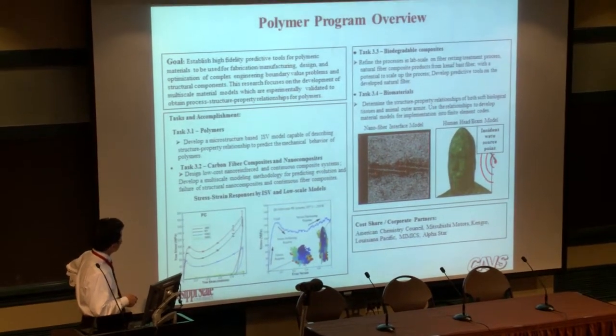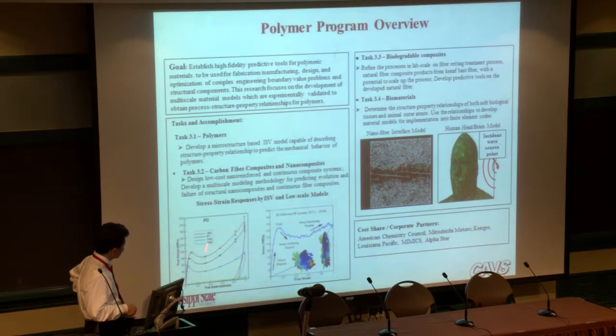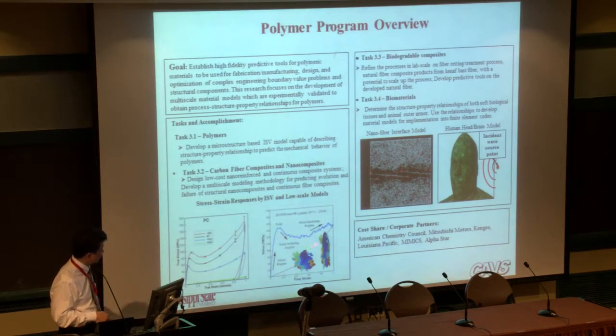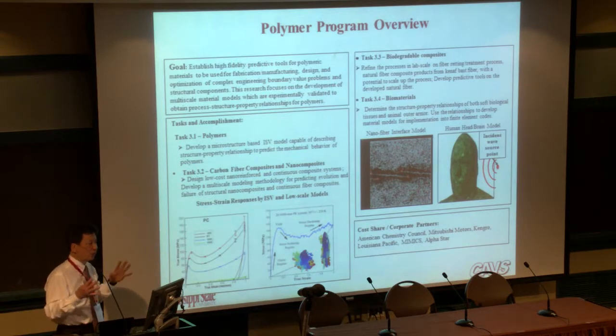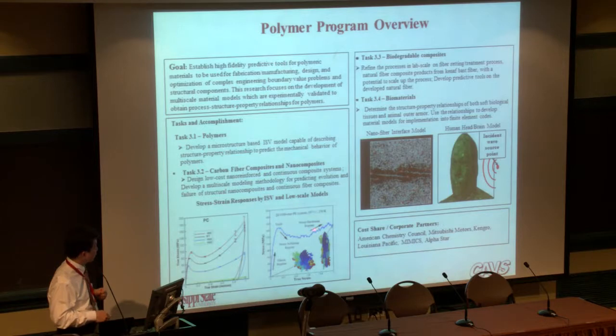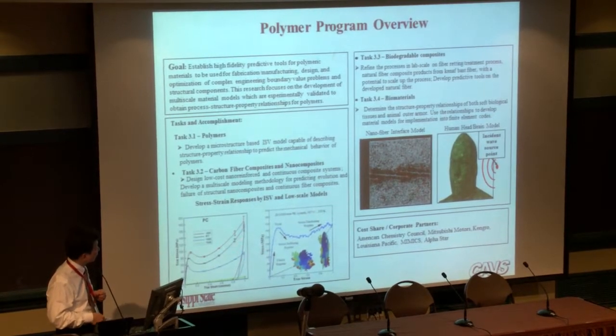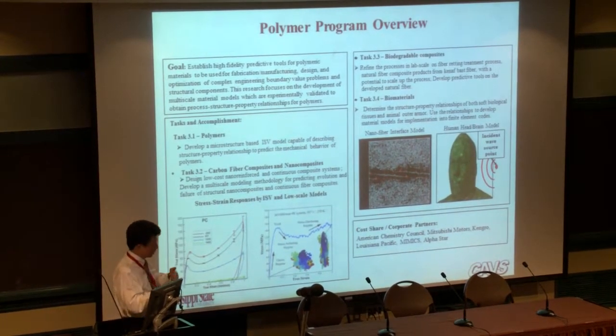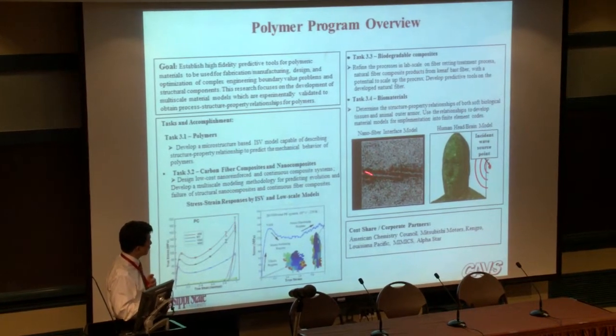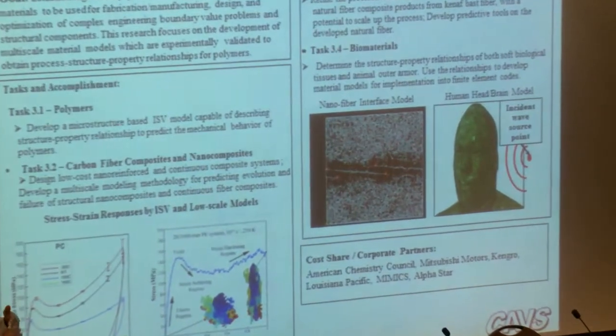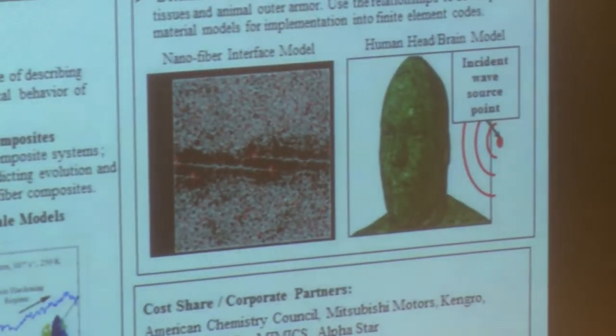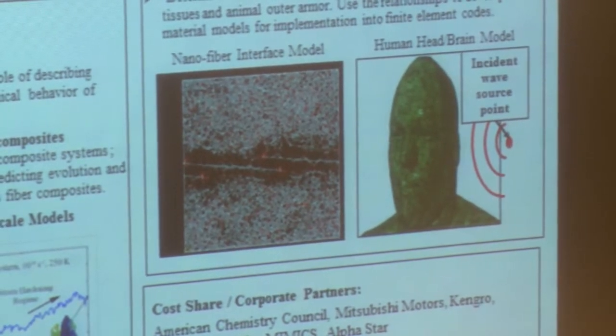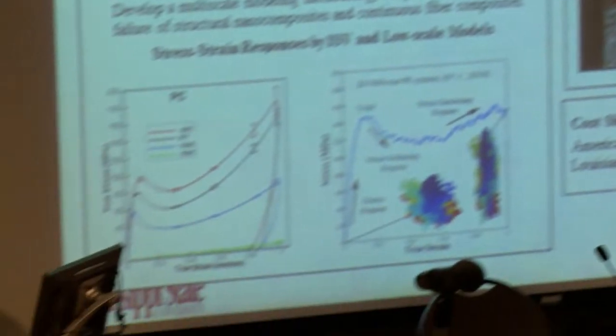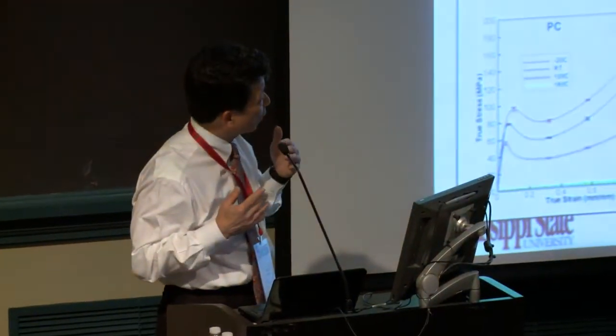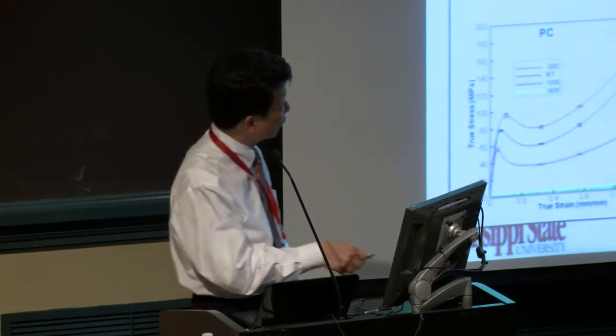And then the polymer program, to the point where we have a certain internal state variable model, but we also run into the molecule area, trying to assemble a large number of molecules and look at the stress strain curve and the damage area. So this is eventually going to connect the bridges and doing the design. In fact, for some of the composite interfaces, you can address numerically what the interfacial strength is between the matrix and the fibers. And on the right side, the biomaterials work looks into high rate impact and explosive loading on brain injury or the lower limbs and so on. So that becomes another branch of the research.